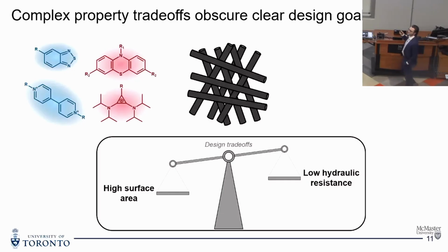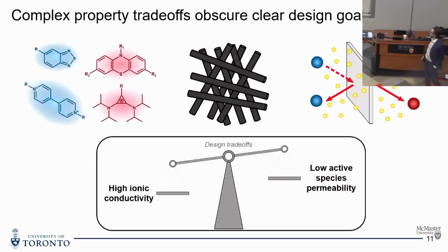Likewise, for our electrodes, we want something that has high surface area for electrochemical reactions. But if we go too high surface area, we restrict porosity, and we're pumping electrolyte through these electrodes. So we induce a lot of pressure drop, and then we have to pay an energy penalty to actually pump electrolytes through these materials. So we need to strike a balance between hydraulic resistance and surface area. And for our membranes, we have a classic permeability selectivity problem where we want high ionic conductivity of our supporting species, but we also need to limit our active species permeability, as we don't want to lose energy, and that's going to compromise our long-term stability of the system.